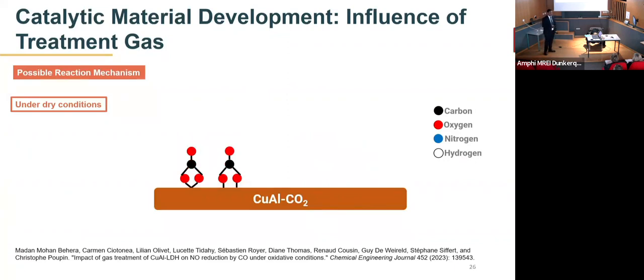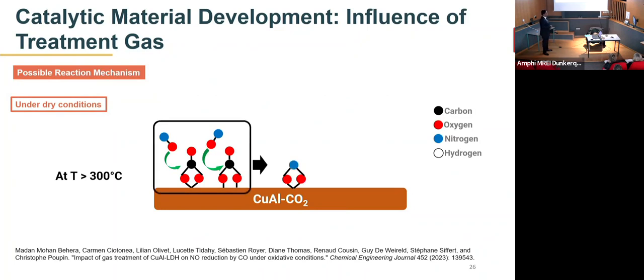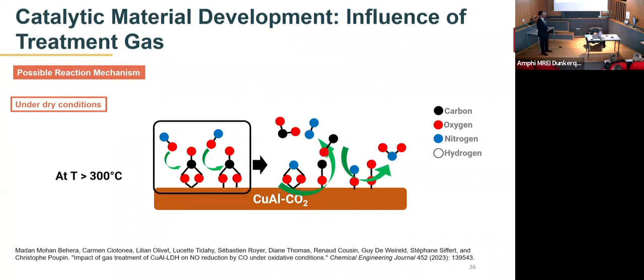However, in case of the copper aluminum CO2 sample, or the carbon dioxide treated sample, we already have bidentate carbonates available on the surface of our catalyst, and at temperature more than 300 degrees Celsius, the nitrogen monoxide from the gas stream can react with these bidentate carbonates to form the bidentate nitrate species, which are generally active for the NO reduction activity, and they react with the carbon monoxide, which is adsorbed on the catalytic surface, to form carbon dioxide and dinitrogen. However, at the same time, there is adsorption of nitrogen monoxide on the catalytic surface, which again reacts with the oxygen that is adsorbed on the catalytic surface to form nitrogen dioxide, which is why we see NO oxidation yield under the dry reaction conditions for our CO2 treated sample.